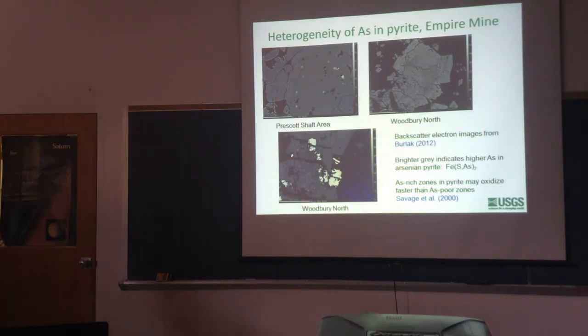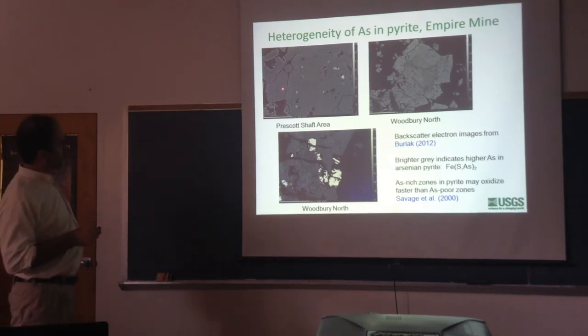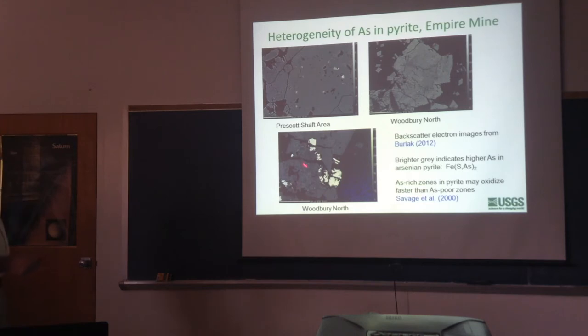And as part of Tamsin's thesis, she looked at, again, the pyrite, and they actually cut it out of the pyrite. It's a little subtle, but can you see the different colors of gray over here? And again, the brighter color represents higher arsenic. And there's also, even more subtle over here, some zones that have slightly brighter gray and darker gray. That represents heterogeneity of the arsenic content of the pyrite. And it's clear down here as well.